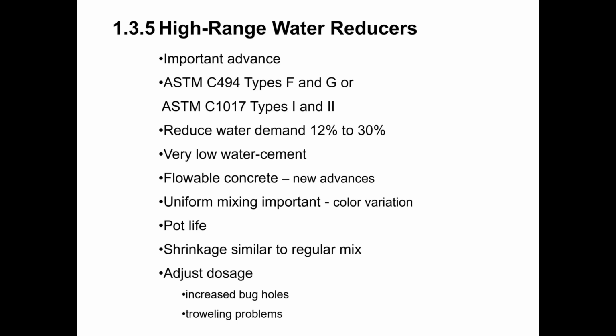Now keep in mind that there are also some drawbacks to using high-range water reducers. One of those is that the fresh concrete tends to be fairly sticky. And so if you have a finisher who is accustomed to working with non-plasticized mixes, and then they start having to finish a mix that does have a super plasticizer, they may complain a bit because it is definitely a stickier texture. They'll get used to it over time because the advantages to using high-range water reducer definitely outweigh the disadvantages. So another name for a high-range water reducer is a super plasticizer. So those two terms can be used interchangeably. High-range water reducer, super plasticizer, those refer to the same type of admixture.